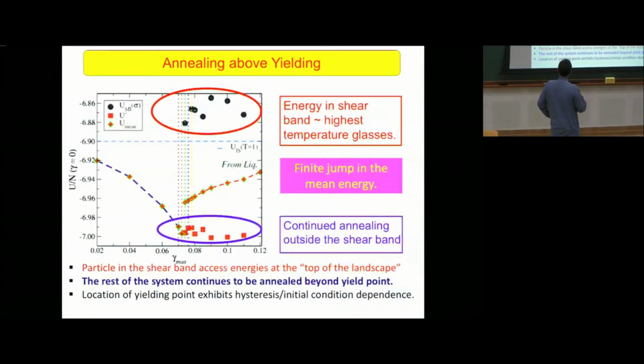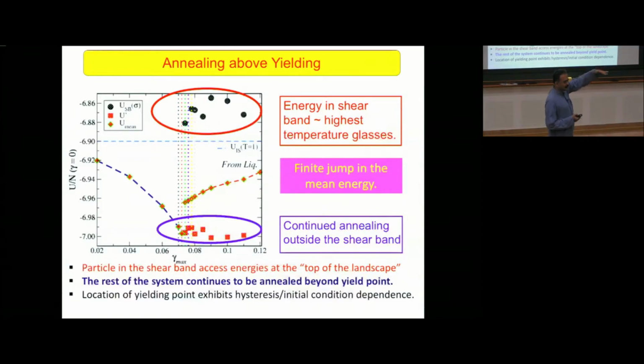And this is illustrated here again. These are the energies that I showed earlier below the yielding point. Now, this is the total energy of the system above the yielding point. One thing that I didn't have earlier is a clear characterization of the discontinuous change, which we do now. If you look outside the shear band, these energies, maybe in a different fashion, keep going down. And in the shear band, you go to energies that are at the top of the landscape, as I mentioned, the worst possible energies. These are actually even a little bit worse because the density of the material has changed, so that one has to factor in.